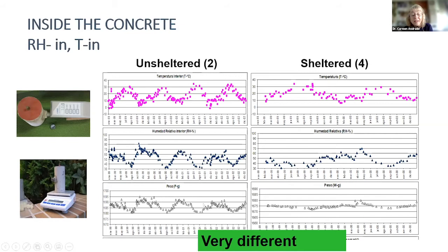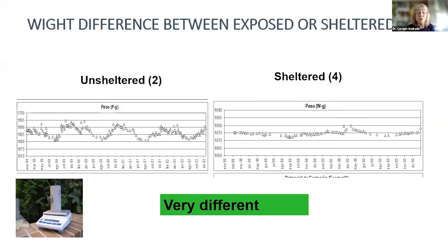The weight in the case of the specimens exposed to rain is much higher, and the changes are much higher than inside. Inside the concrete, if it is not raining directly, although the relative humidity is very similar to the outside, the amount of liquid water that we have inside is much smaller. And this is explained here, it is much larger when exposed.